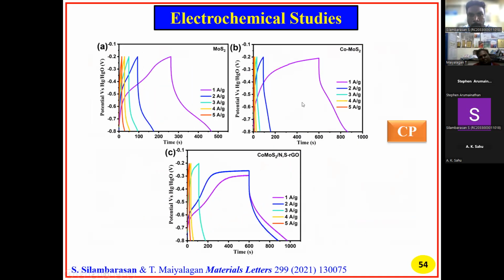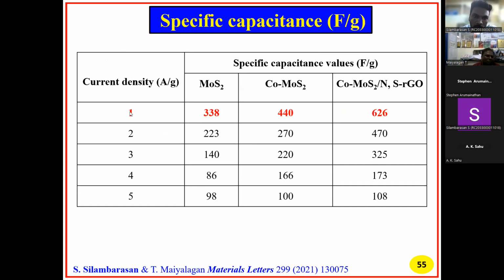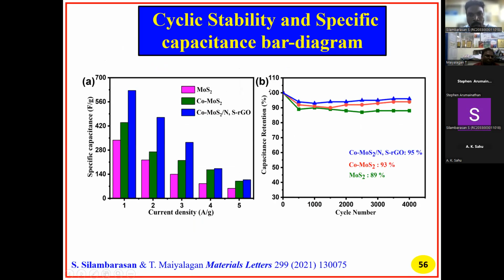So next one, the charge and discharge. Here, compared to the pure and doped samples, the composite gives more discharging and more specific capacitance. Moving to the next slide, at a current density of 1 amp it is around 626 farad per gram. Next, the cyclic stability and the bar diagram of current density versus specific capacitance. The cycle stability was measured over 4000 cycles, and the retention percentage of our composite material is 95%.